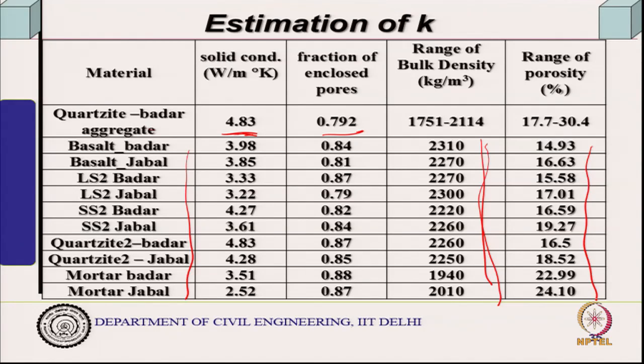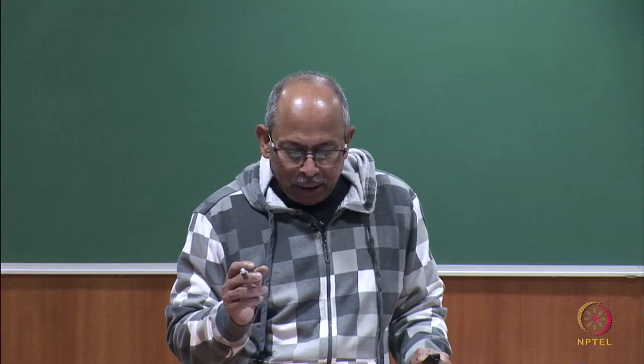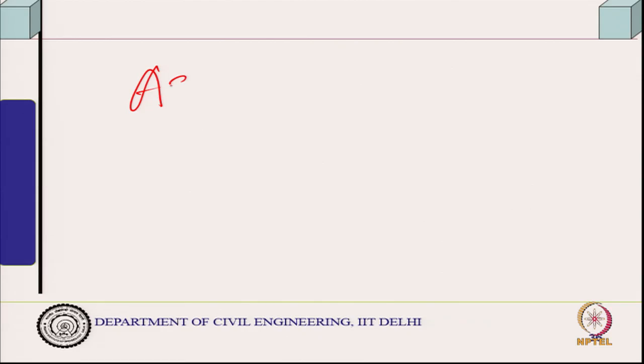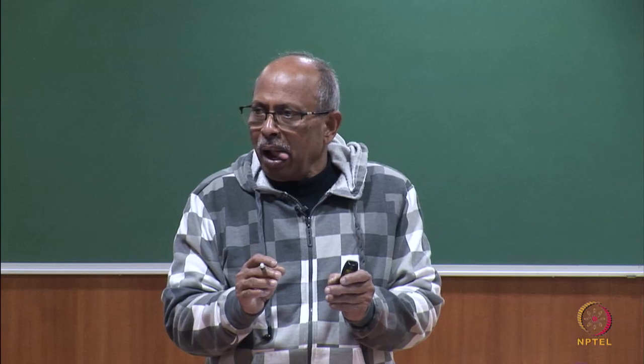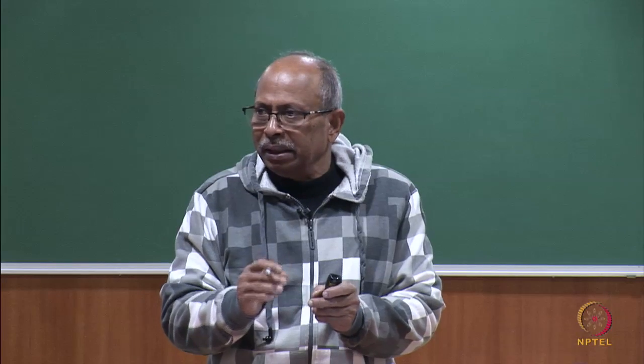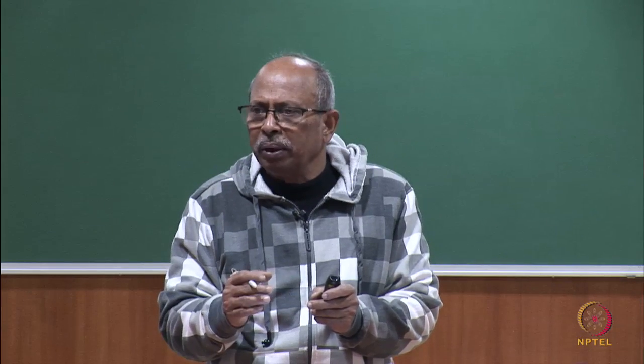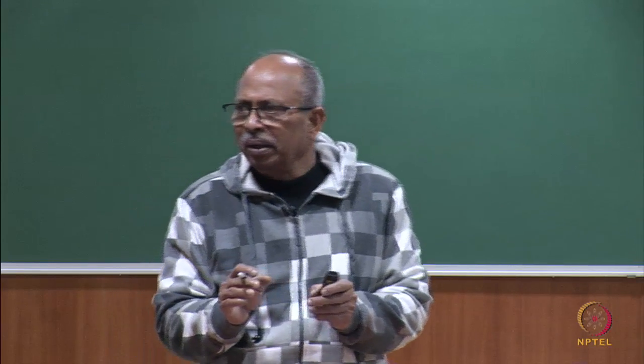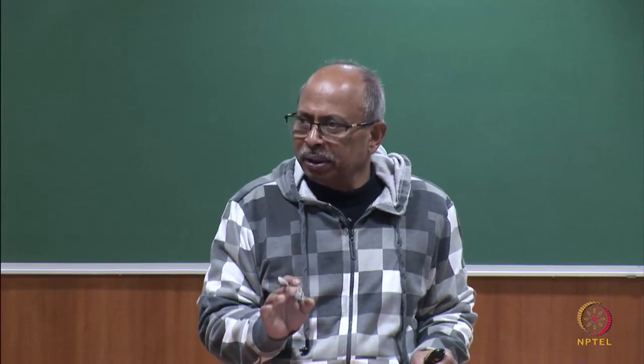Simply, porosity can be measured by, I will just tell you how you measure. I think I might have told somewhere, ASTM procedure C642, I think, water permeable porosity you can find out. Make a block, put it in water for 48 hours, see the mass change and put it for another 24 hours and see the mass change. If the mass changes in the two cases are not very different, then you assume that is the saturated state.